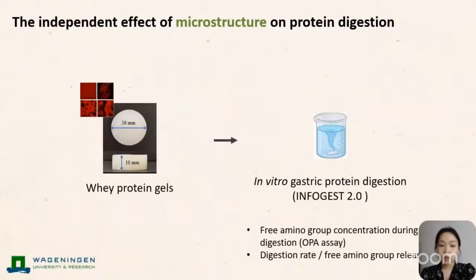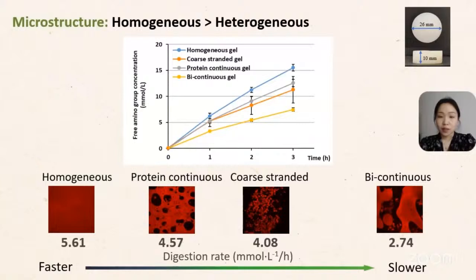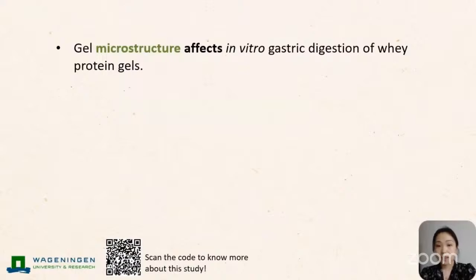Now we put these whey protein gels with different microstructure into the in vitro gastric protein digestion model. We used a static INFOGEST protocol, and then we measured the free amino group concentration during the digestion, and based on this, we calculated the digestion rate, or the free amino group release rate. So for the result, we found that the homogeneous gels showed the highest digestion rate, followed by protein-continuous, coarse-stranded, and bicontinuous gels. This means that the gel microstructure itself can affect in vitro gastric protein digestion of whey protein gels.